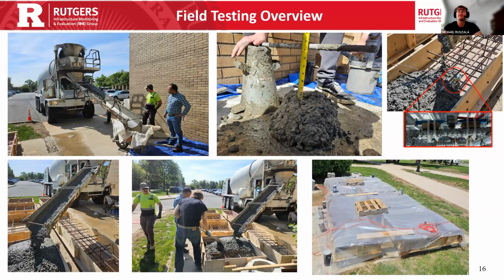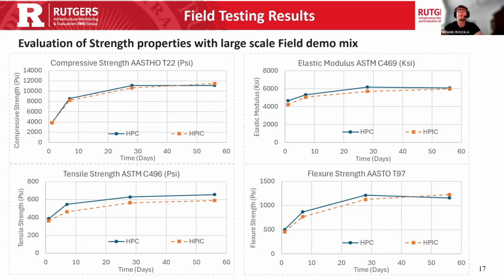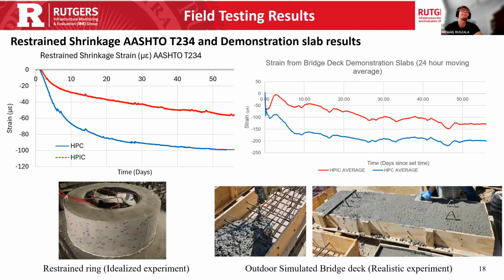So going into the actual demo, we saw that the differences between fresh properties and workability were very minimal. Castability was about the same. There weren't really any differences when finished. You can see the material being discharged, and you can see the sensors being embedded into the mix and the curing practices and finishing that took place. And going into the strength properties of the field mix, we saw very good results. Both of these materials perform very similarly, and both had a high strength that was reported.